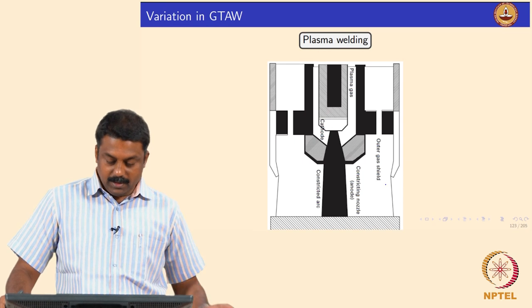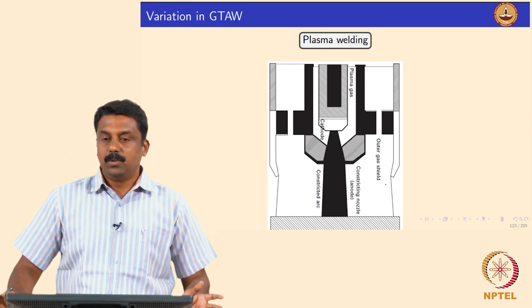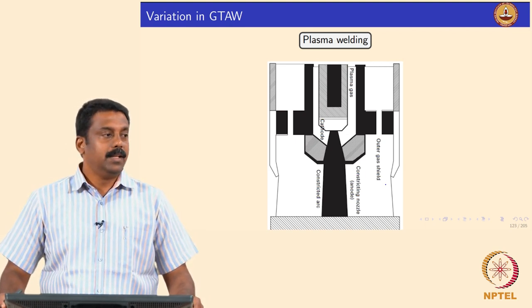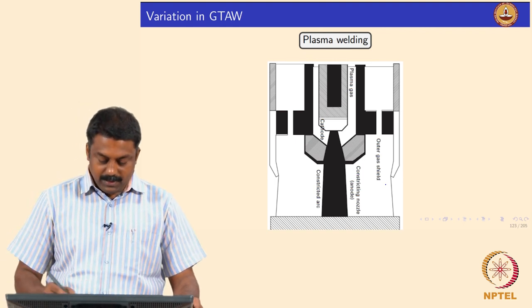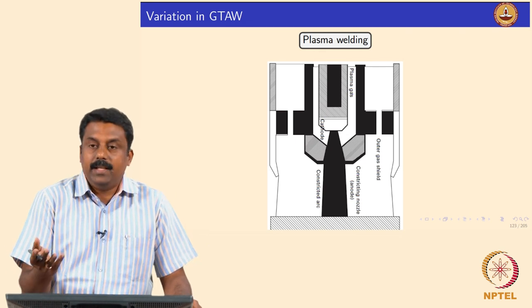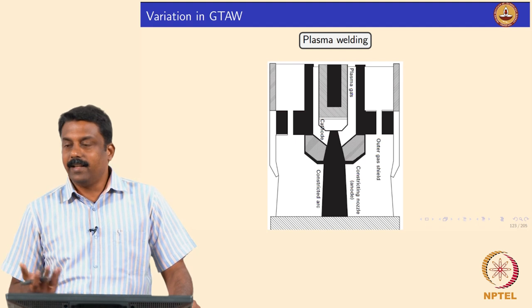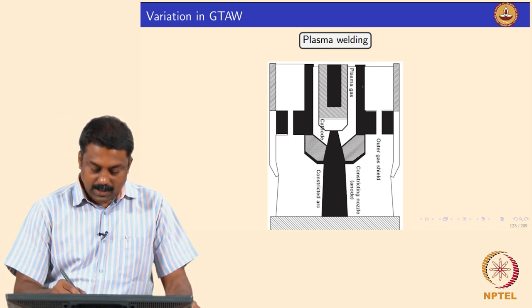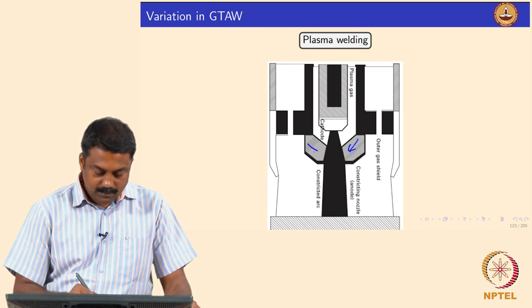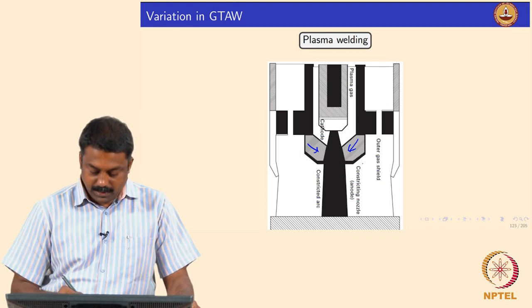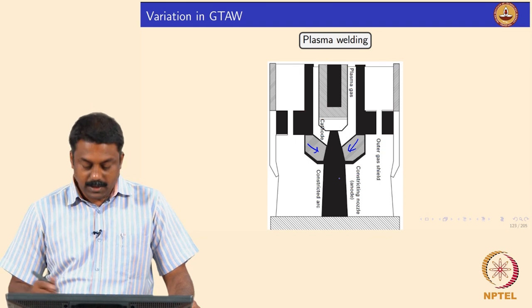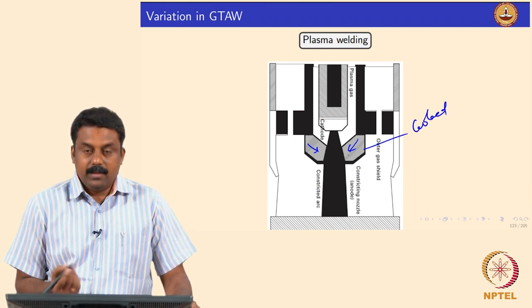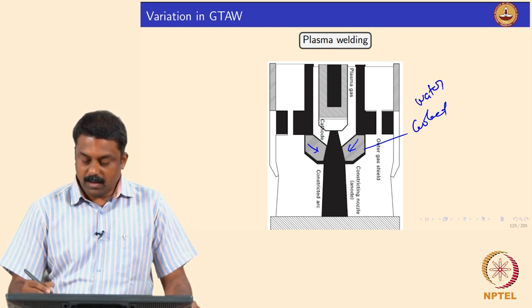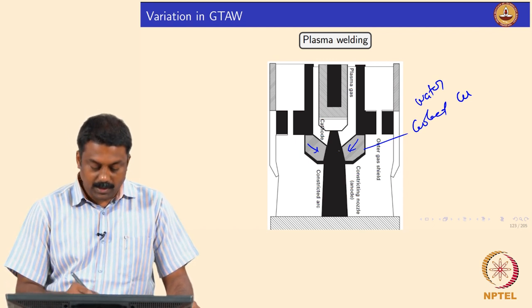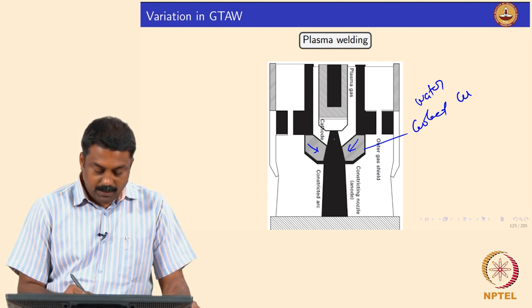We will look in detail at plasma welding, where you use two gases instead of one. One gas is the plasma gas, the other one is the cooling gas or outer gas. Typically, we have a plasma gas, which is the gas used for striking an arc, or in this case plasma. And then we use another additional orifice, and this orifice passes the constricting gas. Generally this nozzle is cooled, otherwise it will heat up significantly. So we generally use water cooled copper nozzles to send the outer constricting gas, so that we can form a plasma jet upon the constriction. So, you form a plasma jet.